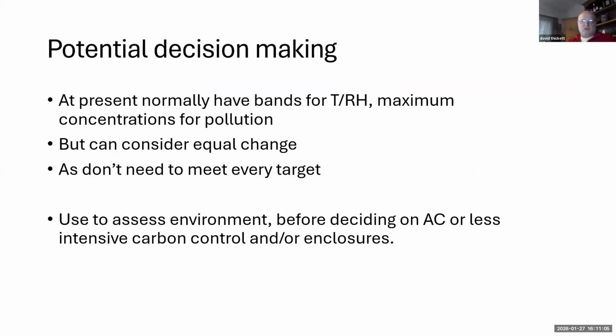But another approach is to consider equal damage, equal change. So we're taking the approach that conservation is managing change, and we don't need to meet every one of those targets because sometimes the NO2 is higher, but the RH is lower. And what we think we can do with this is to use it to assess an environment, either measured or modeled for a new building, before deciding on whether we need air conditioning or something less carbon intensive or enclosures.